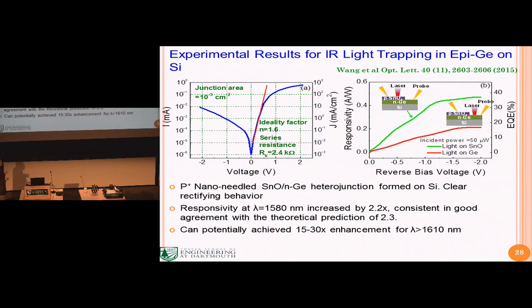So we made a diode using this P-type tin monoxide nanoneedle structure on germanium, on silicon. Indeed, we proved this is a very nice diode structure. This is a PN junction. Proved this is indeed heavily P-type. And if you want to measure the optical responsivity, we shine the light on it, in this case 1580 nanometer light. You see a strong enhancement in the photocurrent when you shine the light through this nanoneedle structure. Basically, that's enhanced by the light trapping.